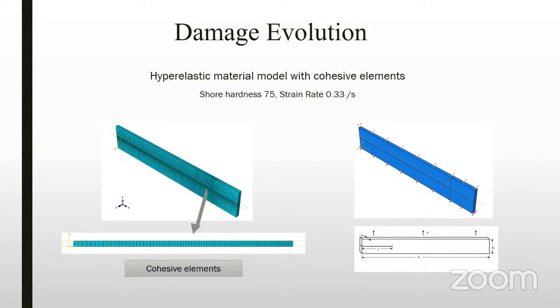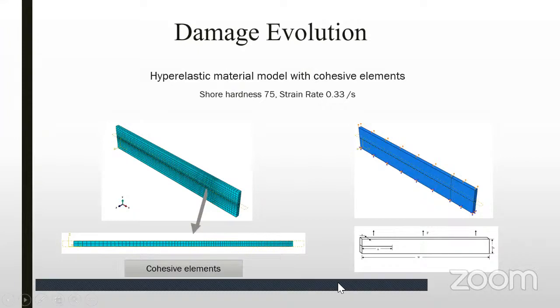To predict the damage evolution in this material, a pure shear specimen was modeled in Abaqus with the material properties of the polyurethane with shore hardness of 75 and a strain rate of 0.33 per second. The elements of the upper and lower sections are related to the hyperviscoelastic material model with the developed user material subroutine equations, and the elements of the middle surface following the crack path are cohesive elements with the bilinear traction separation law.